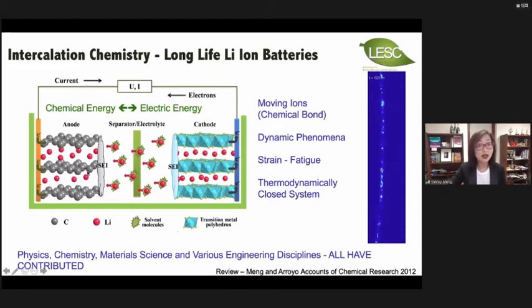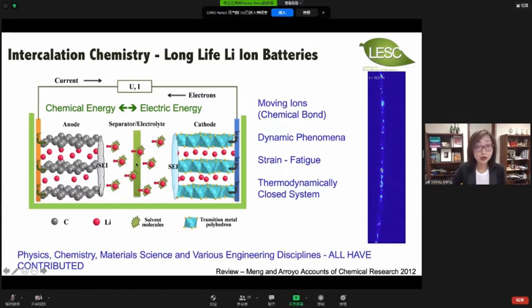So this concept of solid electrolyte interface has been a long-standing challenge for our field. And as we're moving away from intercalation chemistry, for example, the carbon is a layered structure. This carbon is going to be replaced by silicon or lithium metal. These are not intercalation materials anymore. So how can you ensure the electrolyte is still compatible with the new types of anode or cathode materials is a really, really big question.